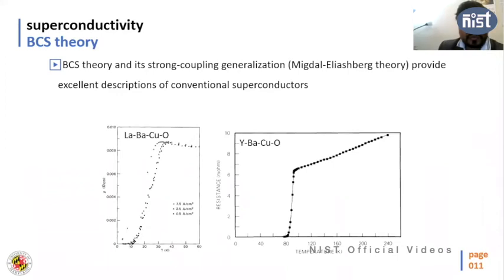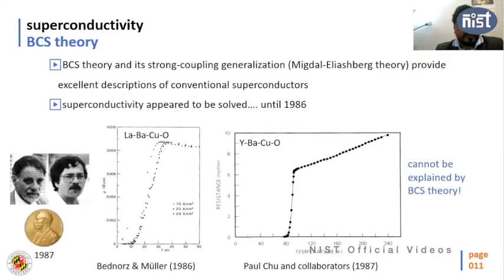It was fine, BCS theory was working until 1986. But in 1986, these two gentlemen, Bednorz and Müller, discovered a new type of material, this lanthanum barium copper oxide. These materials are known as cuprates. And Tc of this material is around 30 Kelvin. The next year, Paul Chu discovered a different material, YBCO, and it shows Tc above liquid nitrogen temperature. Now, this material cannot be explained by BCS theory. So BCS theory failed to explain superconductivity in this material. And these are known as high temperature superconductors or cuprate superconductors. Because of this discovery, in 1987, they got the Nobel Prize.